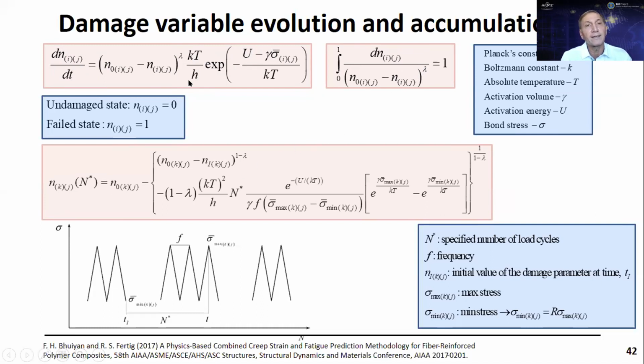And so you can rewrite this in its discrete form. And for a specified number of cycles, which is N star here, you can compute the damage variable. If it's one, it's failed. If it's zero, it's an undamaged state. So based on this criteria, we break the bonds in the model.